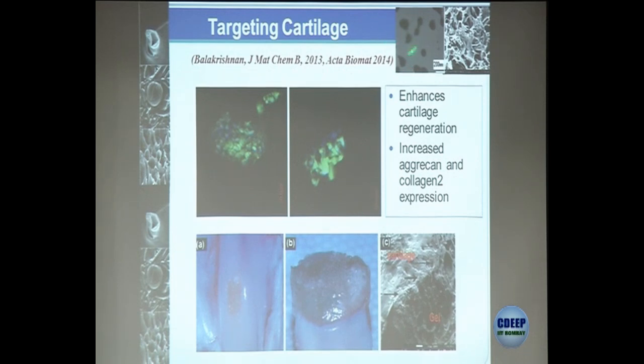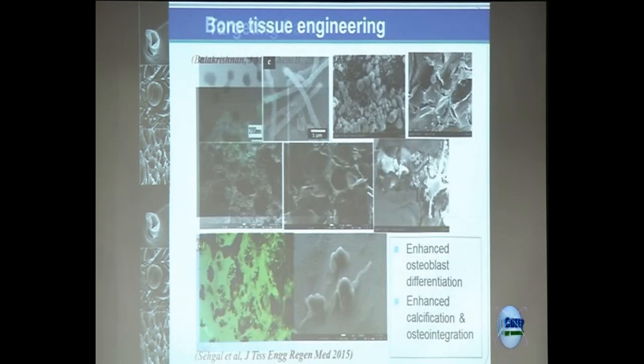So we've developed these nanoparticle in situ gels. We can modulate the porosity, and it actually is bioadhesive. Bioadhesive means it's sticky to the other interface of the tissues. So you can see here, this is the bone and this is the interface where the gel is actually merged with the surrounding structures, and hence this forms a cushion-like matrix and can replace the cartilage function in these joints. Very important because it brings out the possibility of ruling out joint replacement surgeries in this very debilitating disease.